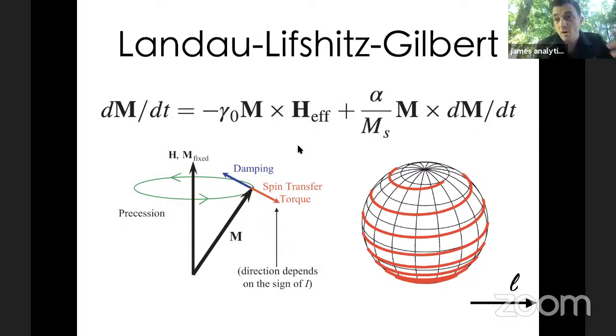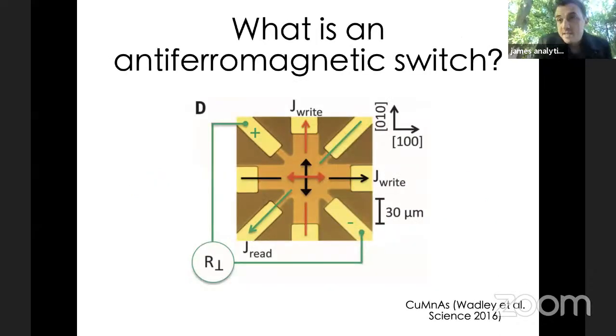But we inherited this language from the ferromagnetic spin torque systems and applied it to antiferromagnets, and now this M, instead of applying to the magnetization of the system, now applies to, let's say, the sublattice magnetization of the antiferromagnetic system. Okay, so in a seminal paper in 2016, Wadley, Jungwirth, and others created these kinds of devices where you could actually apparently observe the rotation of the Néel vector using this kind of system, with theory by Železný and Jungwirth himself, which motivated a lot of these experiments.